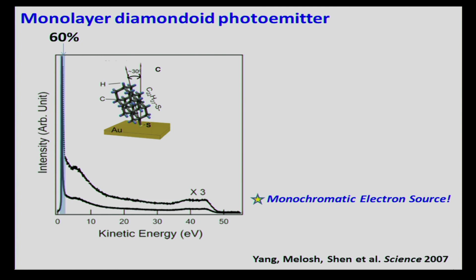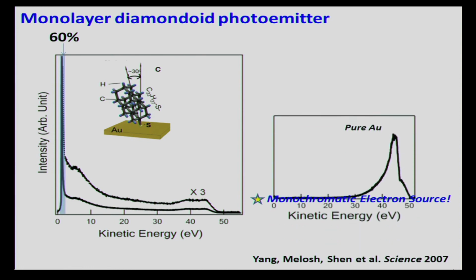So what happens here, as we think, is that because we're having a very thin layer of diamond, and because they're so chemically pure and so structurally pure, the electrons don't behave differently when they come out, as they do with a diamond surface, which has all kinds of defects and all kinds of atomic arrangements and all kinds of local chemical environments, which can all influence how the electrons come out of them. In this case, with a diamondoid, because it's so pure a material and it's only a molecular monolayer thin on a surface, when the electrons come out, they all come out with the same energy. And this is really exciting.